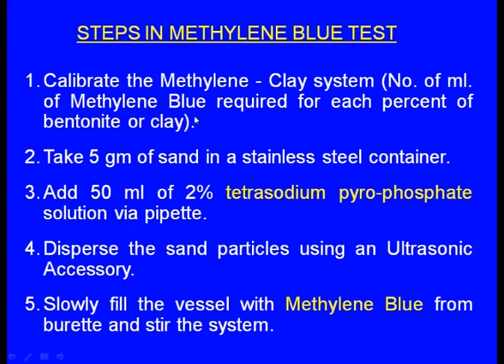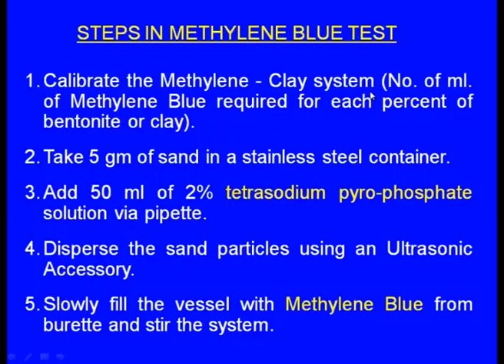Methylene blue solution reacts with the active clay. As long as active clay is present, the methylene blue will be reacting with it and we cannot see any free methylene blue. With prior experiments, we calibrate the methylene blue-clay system — determining how much methylene blue is required for a given amount of active clay.